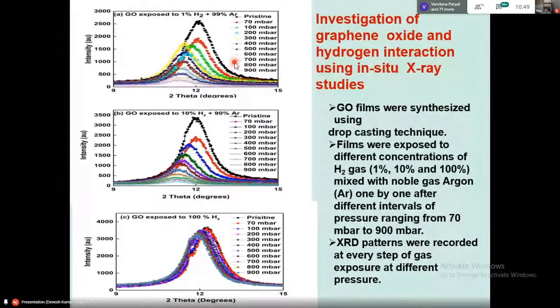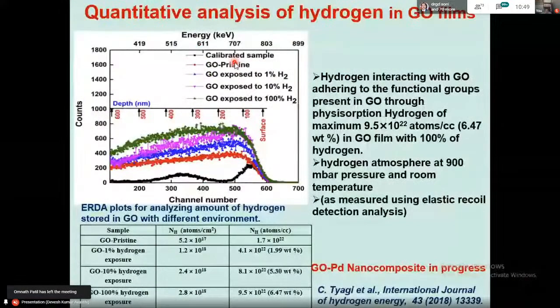When it goes to the lower side, that means the interspacing of the graphene oxide layers is increasing. So that was showing that hydrogen was actually getting absorbed. So we became very much interested in determining how much hydrogen is there. So we did one additional experiment, a quantitative analysis of hydrogen in GO.